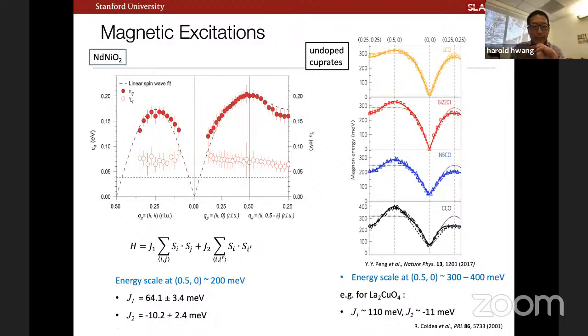So if we look at these excitations in some detail, we find two things. You can reasonably fit the paramagnon dispersion with a two-neighbor magnetic model, and we can compare that with the cuprates for J1 and J2. And in broad strokes, this is for undoped parent compound cuprates. What we find is a magnon bandwidth in the nickelate case of order 200 meV, which is somewhere between 50% to 75% or so of the cuprate magnetic energy scale.